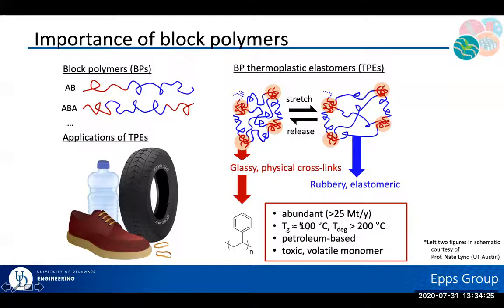Well, the glass transition temperature is analogous in some instances to the use temperature of the material. And if you think about this, you're all familiar with it in terms of a styrofoam cup that I fill with boiling water and it starts to get soft. Right at about 100 degrees is that softening, or in this case, we can call it a glass transition temperature for that polystyrene.